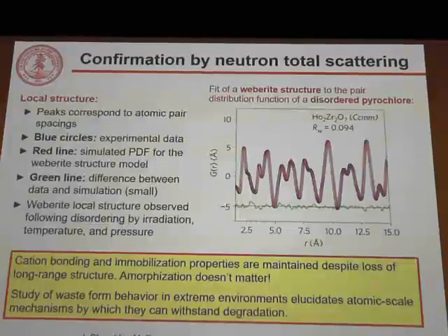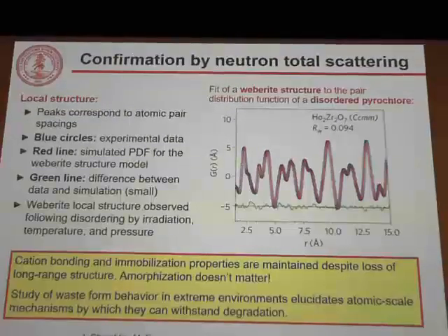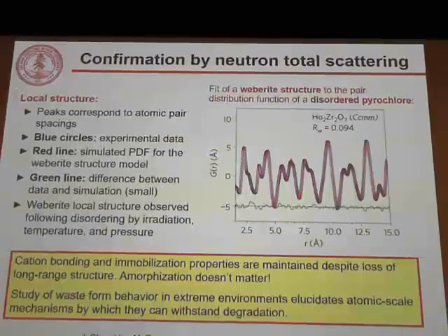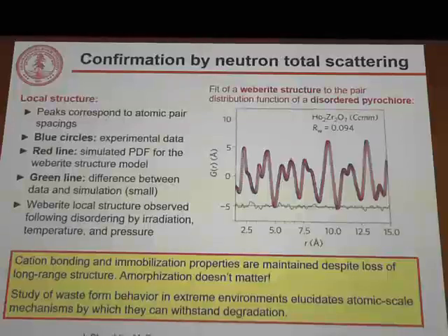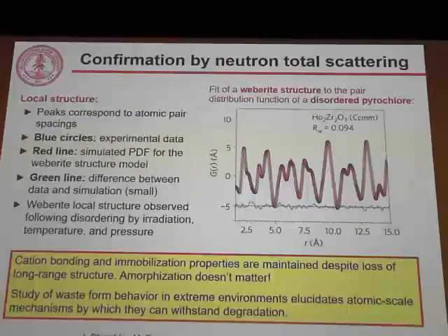So what we've learned from all of this is that the local cation bonding and therefore the radionuclide immobilization properties of these waste form materials are maintained whether or not they lose their long-range structure under irradiation. So counter to what we thought for a long time, amorphization doesn't seem to really matter for this specific property, for the leaching of these materials.